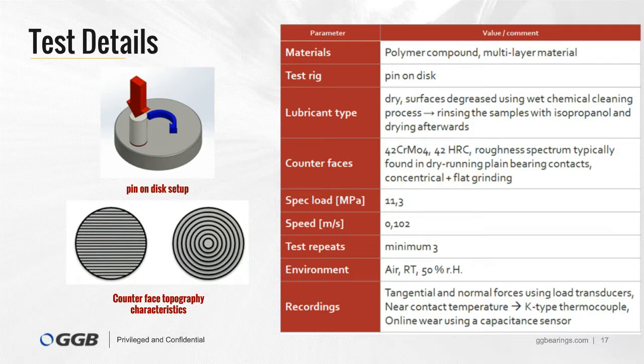This steel disc had different topographies, and the topography spectrum encompasses typical variants used in bearing applications. On one hand, we had a linear flat ground counterface, and on the other hand, we used concentrical grinding to produce the topography shown on the right side of that slide. Both surface finishing methods generate typical anisotropic surfaces, with a clear orientation of the roughness peaks and valleys.